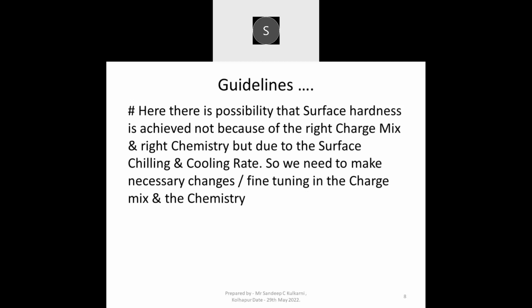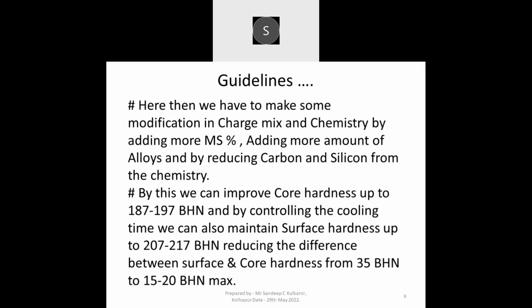Here, there is a possibility that surface hardness is achieved not because of the right charge mix and right chemistry, but due to surface chilling and cooling rate. So we need to make necessary changes or fine tuning in the charge mix and the chemistry. We have to make some modification in the charge mix and chemistry by adding some more percentage of MS, adding some more alloys, and by reducing carbon and silicon in the chemistry as necessary. By this, we can improve the core hardness from 165 to 187, 197 BHN, and by controlling the cooling time or cooling rate, we can also maintain the surface hardness at 207 to 217 BHN. Thus, the difference between surface hardness and core hardness reduces from 35 BHN to 15 to 20 BHN.